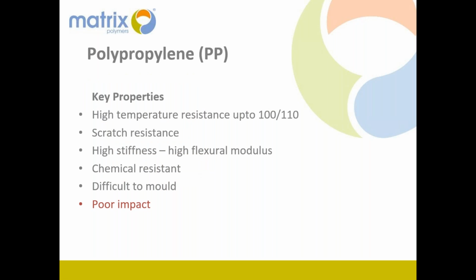So polypropylene, at least as far as rotomolding is concerned, has to be considered only where you need high temperature resistance, higher than what LLDPE can offer. Up to 100, 110 degrees, it is safe to use polypropylene. It has much better scratch resistance, high stiffness and high flexural modulus. Chemical resistance, it is of course a little difficult to mold, and it has relatively poor impact.